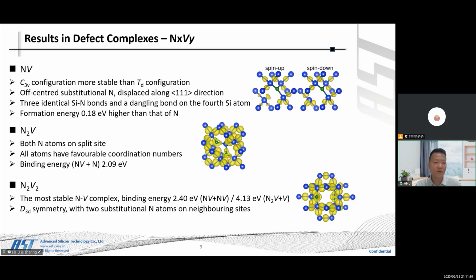For N2V, both nitrogen atoms are on split sites, both atoms having favorable coordination numbers. The binding energy is 2.09 eV. N2V2 is the most stable NV complex. The binding energy is 2.4 eV for NV plus NV, or 4.13 eV for N2V plus an additional vacancy. It has D3d symmetry with two substitutional nitrogen atoms on neighbouring sites.